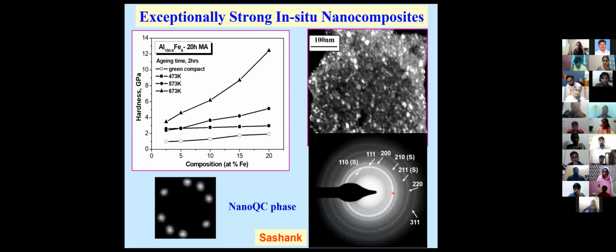One such thing is, because I'm an engineer, that too a materials engineer, we are interested to make materials which are very strong materials. Okay, so for example, aluminum is a very soft material. But if I can make aluminum into nano and embed some particles into that nano, for example, some kind of compounds, you must have heard of various compounds in material science. And if I can take an aluminum matrix and put some compounds such as what is called Al3Fe, and such kind of nanoparticles, if they are embedded into aluminum, you get a hardness as high as 12 gigapascal. 12 gigapascal means 12,000 megapascal hardness, which is much higher than the hardness of a typical aluminum.